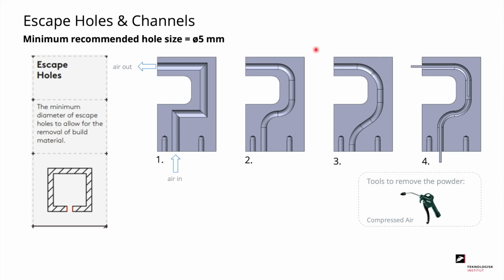When designing these channels, it is important to have curves rather than straight lines and 90-degree angles, as in the design you see to the left. Because in these 90-degree angles, the powder can get stuck and it can be difficult to blow out the powder with compressed air. So rather go for a design like number 3 or 4 in this figure.